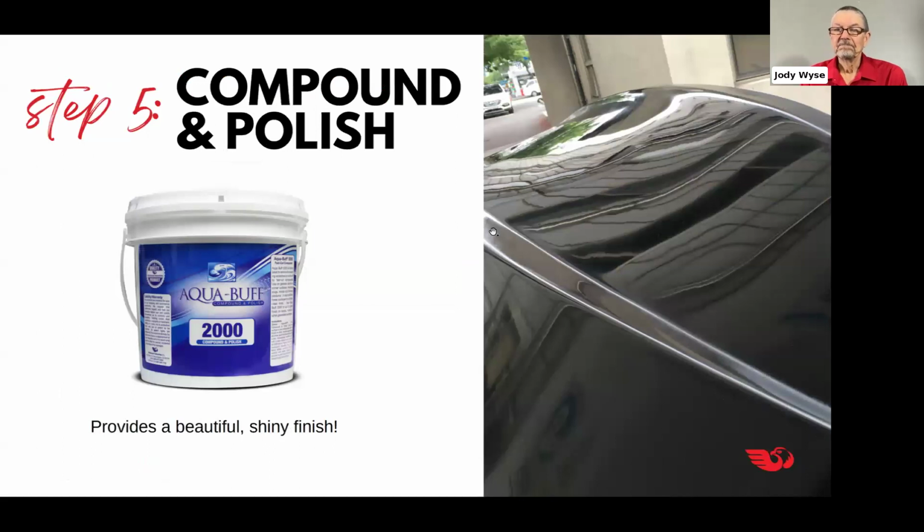Right. After that, we've got the options of buffing and polishing compounds. There are various ones that we carry, the 1000 and the 2000. The 1000 is a very aggressive, fast cut compound. And the 2000 will yield a very nice gloss, and on whites and things like that, it's probably all you're ever going to need. If you're trying to polish out some 600 scratches, the 1000 works the best. Now, if you take one of our primers and sand it on day one, it's going to sand really easy. And the sooner you polish it, the easier it's going to polish. It's going to sand out those buffing scratches easier.